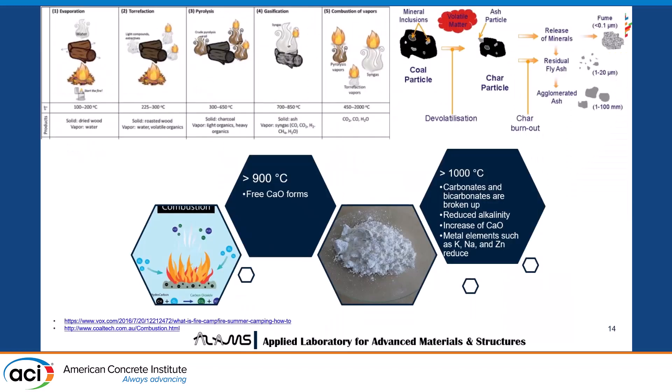This difference occurs because of the temperature at which the ash is burnt. Coal fly ash is burnt at 1100 to 1700 degrees Celsius, whereas our wood ash was specifically burnt at 850 degrees Celsius at the facility. At higher temperatures all the minerals get fully burnt, while at lower temperatures the charred particles remain — that is why we found all the charred particles.